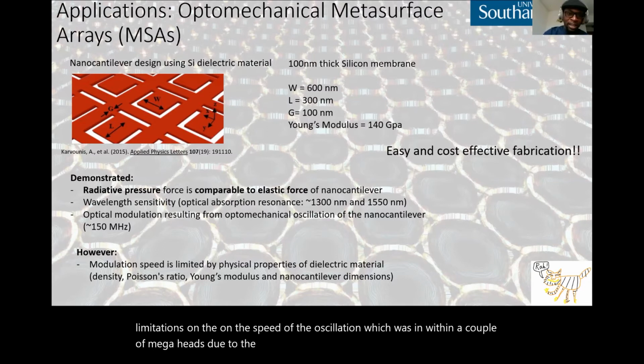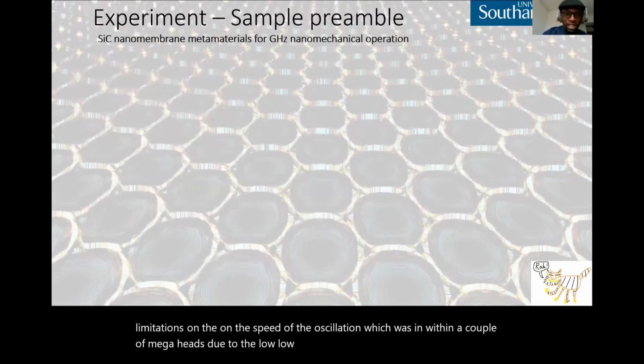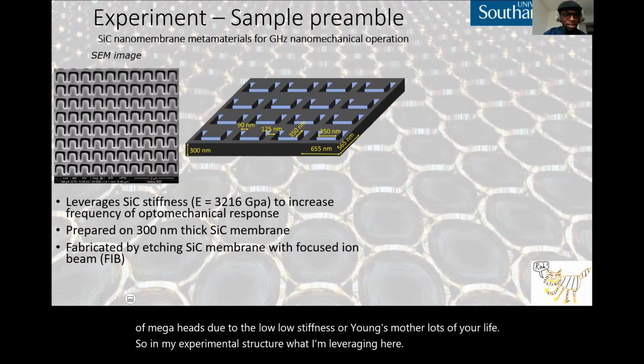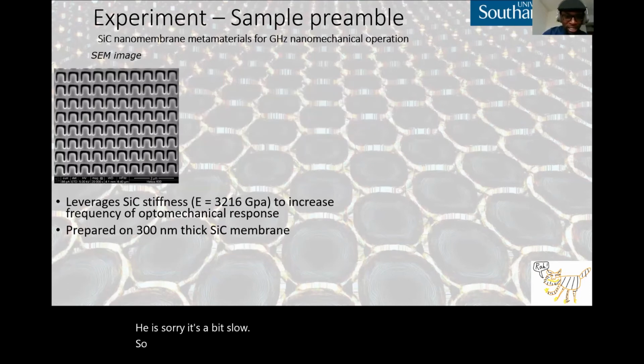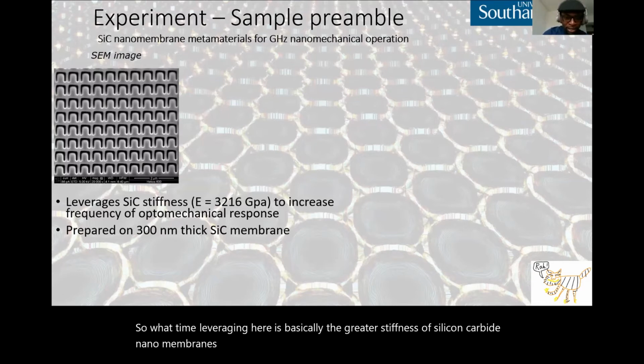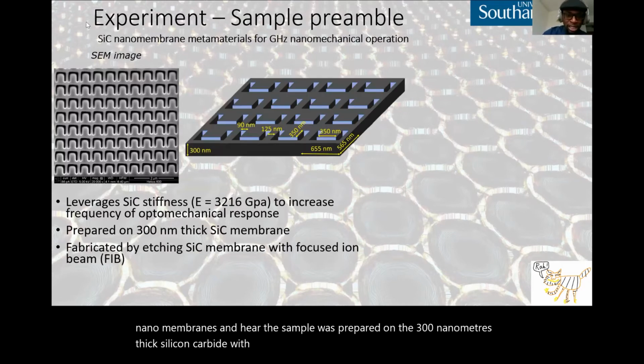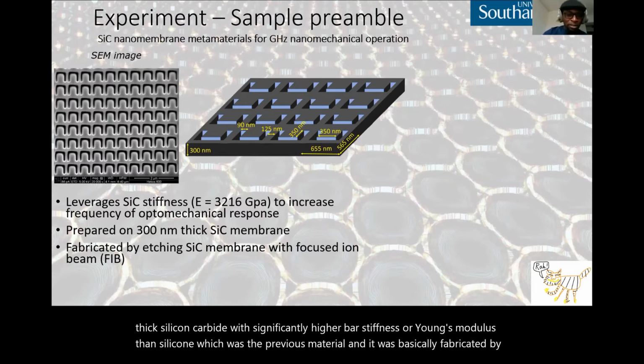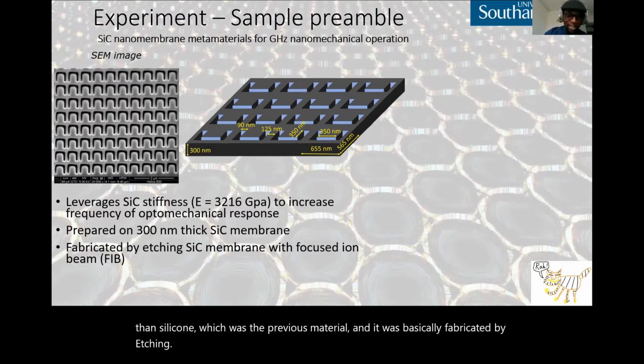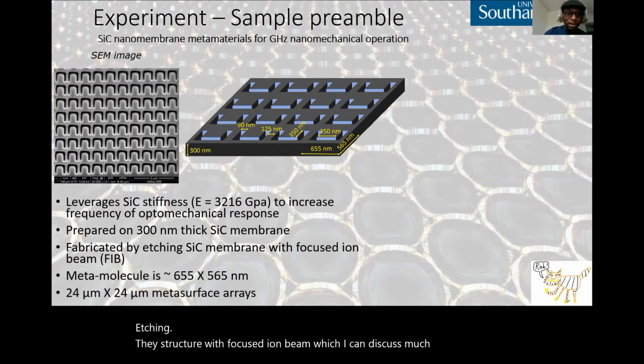So in my experimental structure, what I'm leveraging here is basically the greater stiffness of silicon carbide nanomembranes. The sample was prepared on a 300 nanometers thick silicon carbide with significantly higher stiffness, or Young's modulus, than silicon, which was the previous material. And it was basically fabricated by etching the structure with focused ion beam, which I can discuss much later if anyone has questions about it.